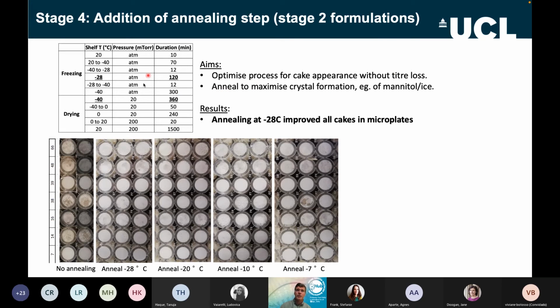So we tried that. We tried a different set of annealing temperatures from -28 up to -7, and we could see, compared to no annealing, everything improved. -7 was perhaps still a bit patchy, but somewhere between -10 and -28, we were getting reasonable consistency across the formulations compared to having no annealing. So annealing was having a good impact on the cake structure. So we took that forward.